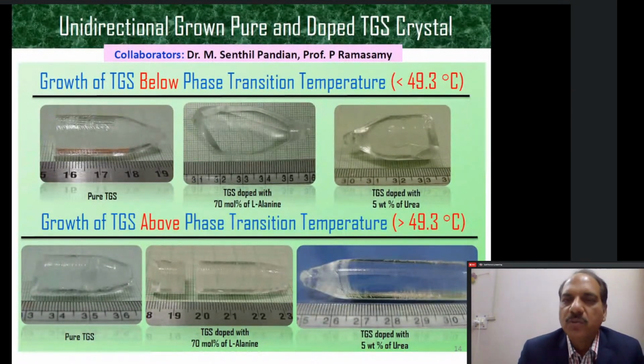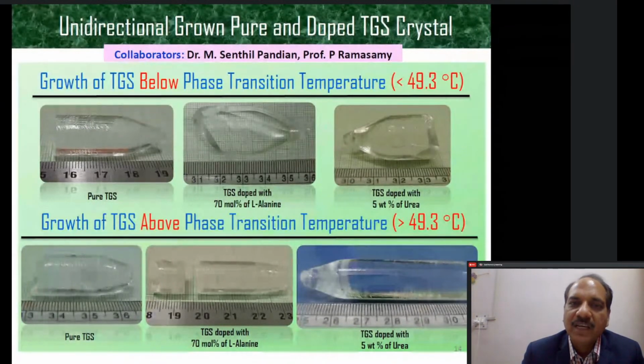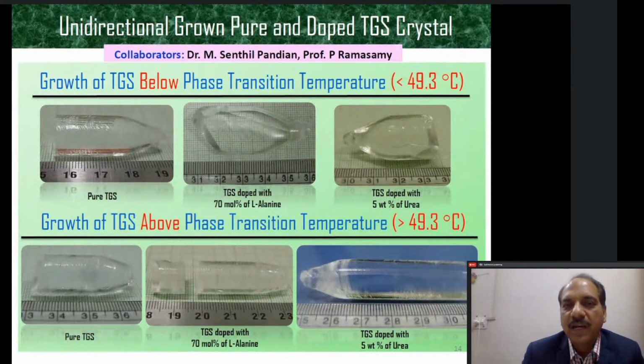So we thought, why not use this property of this self-poling material, triglycine sulfate. The main motivation for growing this material above and below the phase transition temperature was the solubility of TGS above 49.3 is very high, and below 49.3 is less. So we thought if we can utilize this high solubility above 49.3, we can increase the growth rate, and we can grow a very large crystal in a lesser number of days. And then because we are anyway below the phase transition temperature, it will automatically come back to its ferroelectric state, which we really wanted, right?